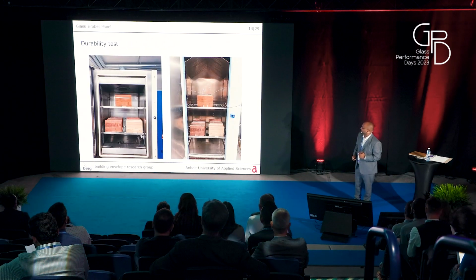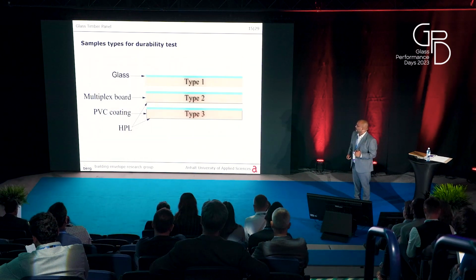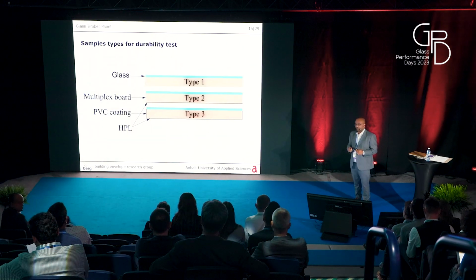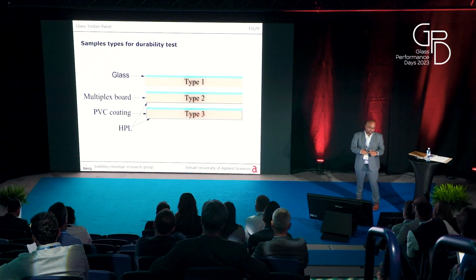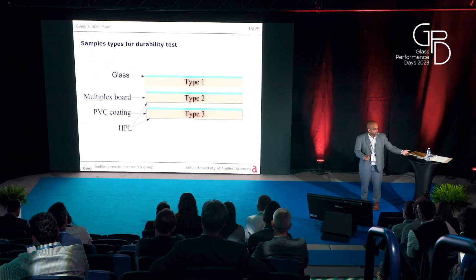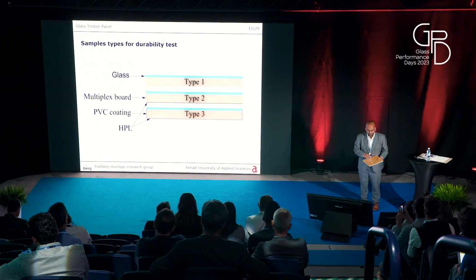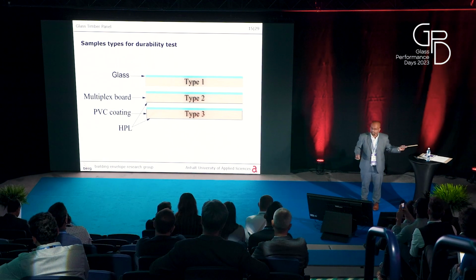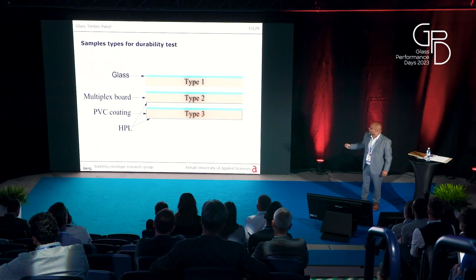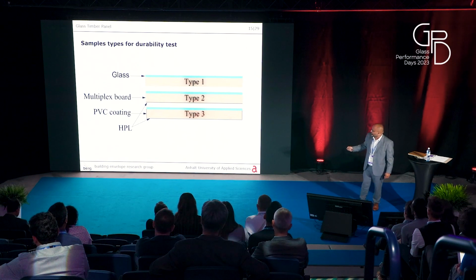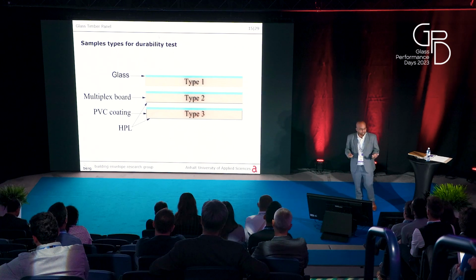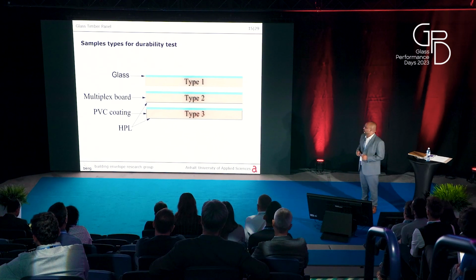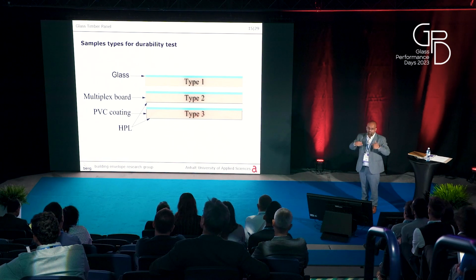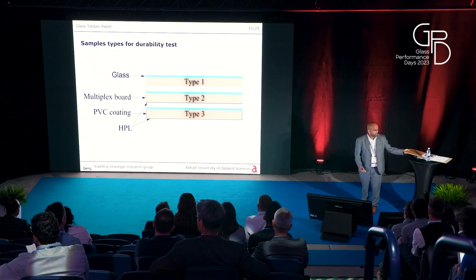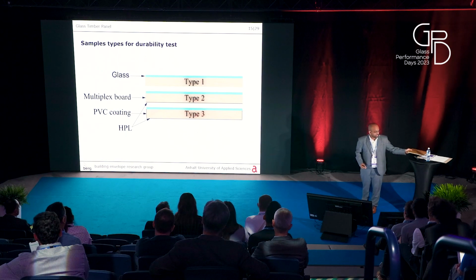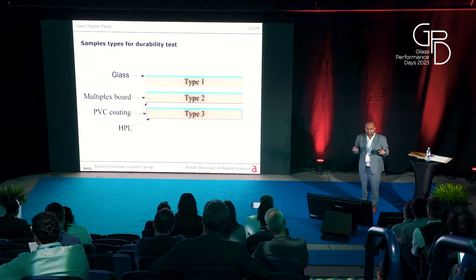These are some examples of the durability test. And we tested 3 different types of samples. Since in the furniture industry, they usually laminate the glass on one side with the veneer and the other side with plastic, we tested 3 different types. In type 1, all the sides are free, so they're not treated with any plastic, and they allow moisture penetration. In type 2, the edges are free, and the bottom side is laminated. And the third, type 3, all the sides are laminated with the plastic.